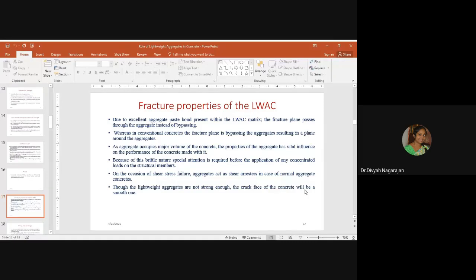Due to excellent aggregate paste bond present in the lightweight aggregate concrete matrix, the fracture plane passes through the aggregate instead of bypassing. Actually, the lightweight aggregates will be porous in nature. They will have surface pores and voids, and will have an excellent aggregate paste bond. So the fracture plane passes through the aggregates. That is, the aggregate splits into two halves when subjected to testing.